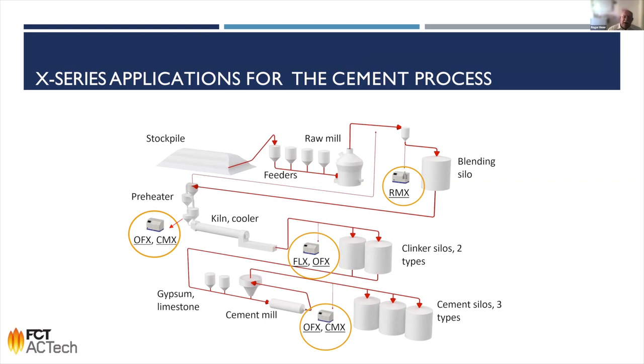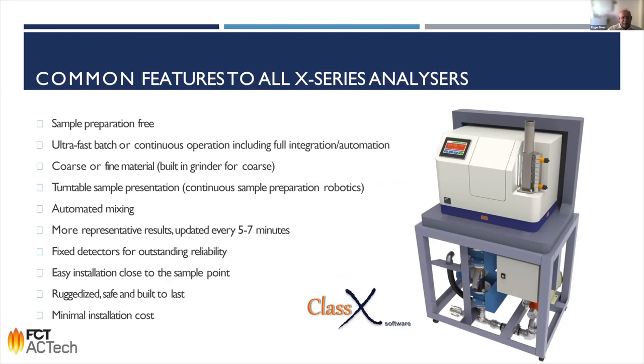Later in the process, we have the OFX, the FLX, and the CMX machine, which I will show you a little bit later the details about, where you get a combination of XRD and XRF to really have a good grip on your process. All the machines are super compact. For your information, the size of this gray box with the blue bottom is about 80 by 60 by 50 centimeters. And the huge difference between a conventional lab analyzer and our equipment is that we do not prepare